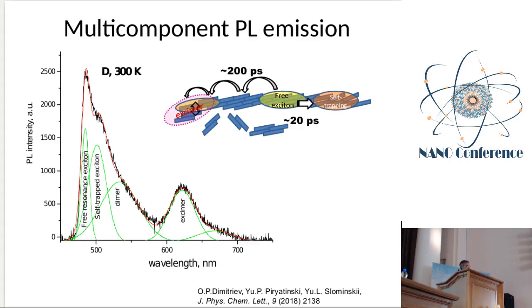Moreover, the photoluminescence emission of J-aggregates has several components. We can decompose the emission spectrum into at least four components which correspond to free resonance exciton emission, self-trapped exciton emission, dimer emission, and excimer emission. These components are illustrated schematically in this picture. When we have excitation of a free exciton, it can relax through interaction with vibronic modes and give a self-trapped exciton, or it can diffuse to specific sites where it interacts with the dimer species and creates excimer emission.